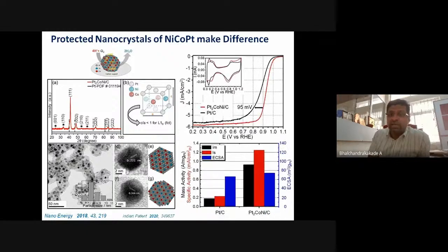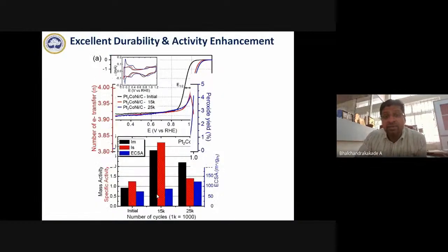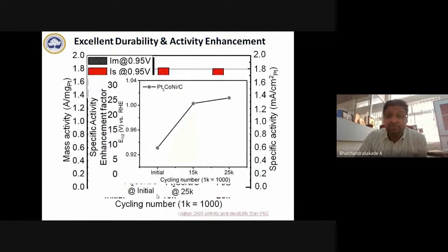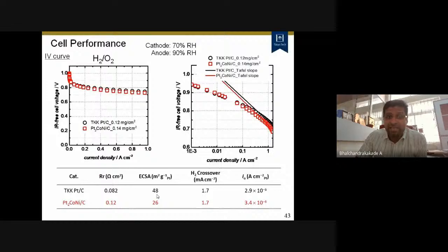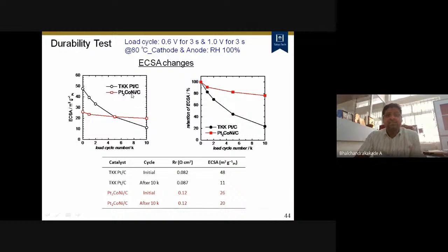Here you can see that the activity of Pt2CoNi is much higher than the commercial platinum. The idea here is that when I add some foreign transition element into the platinum matrix, I can increase its stability as well as the activity, and such materials can be used in the device part of the fuel cell. So I will show one application here, how it works. TKK is a commercial platinum catalyst, and Pt2CoNi is our catalyst.